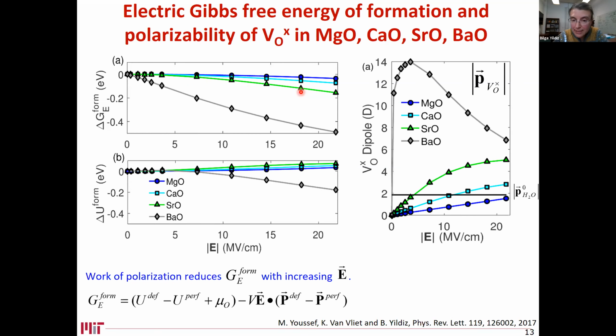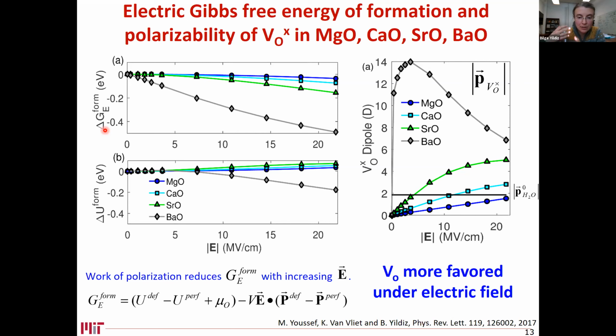And this is because the net dipole introduced because of this defect in the system is positive. So as a function of field, the net dipole introduced via the oxygen vacancy is positive. So this term is positive, and therefore the Gibbs free energy of formation for this defect becomes more negative. And so this is telling us that such an important defect with a trapped charge that becomes color centers, that can give magnetism, that can influence the electronic properties, become more favored under electric field.